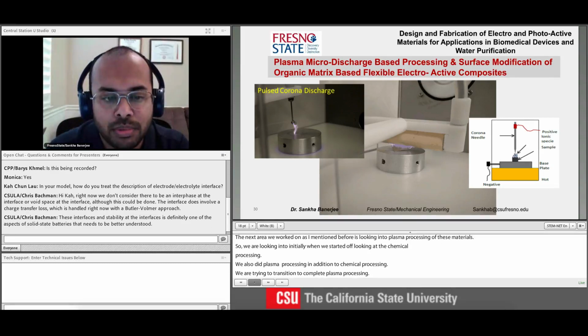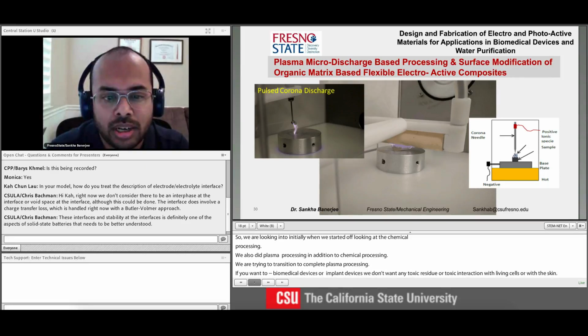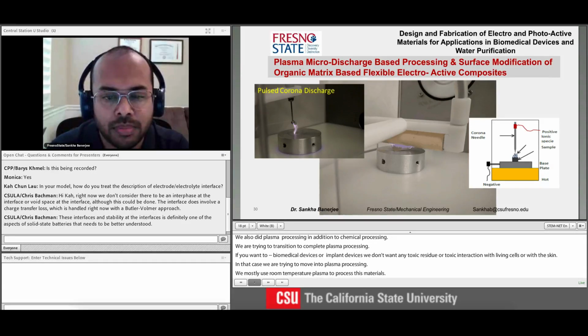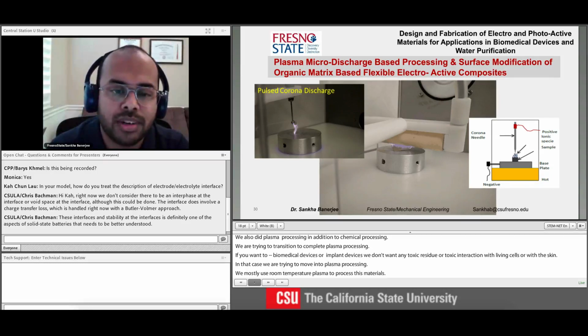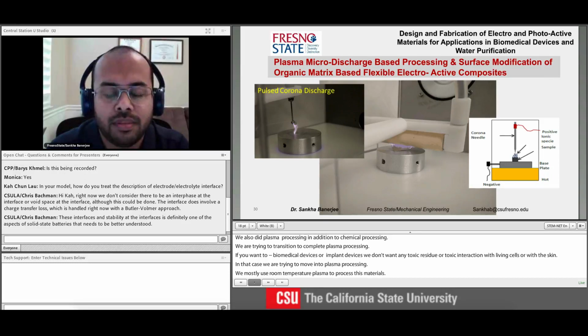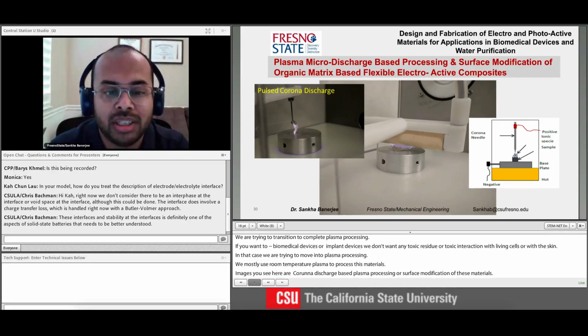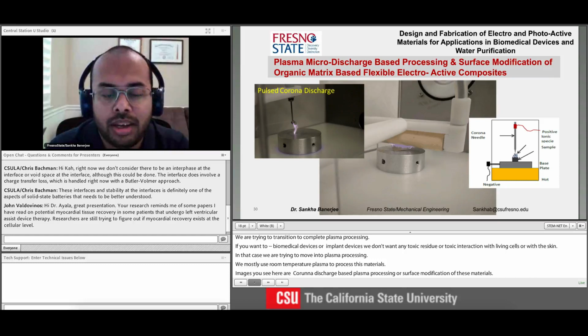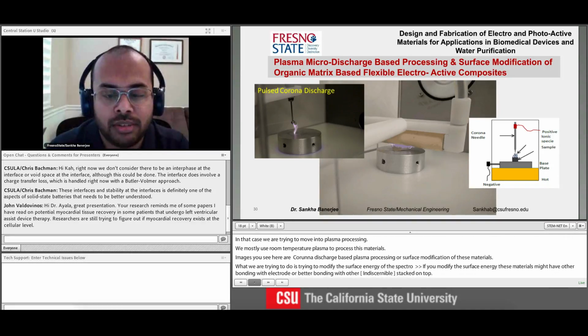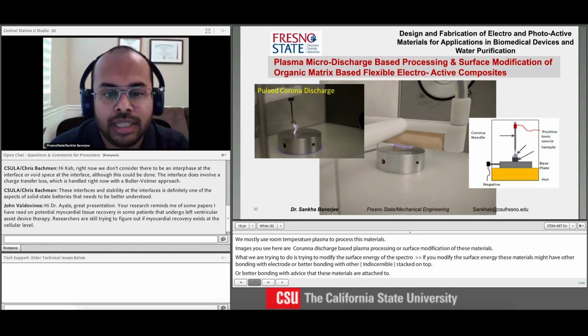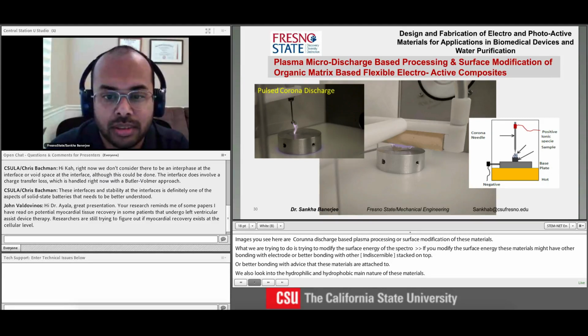We mostly use room temperature plasma to process this material. The images that you see here are corona discharge based plasma processing or surface modification of these materials. What we're trying to do is modify the surface energy of these materials. Now, if we modify the surface energy, these materials might have better bonding with the electrode or better bonding with other thin films that are stacked on top, or even better bonding with the device that these materials are attached to. We also look into the hydrophilic and hydrophobic nature of these materials, and that might also help us in developing scaffolds and also growing specific kinds of cells, and also inhibit the growth of, let's say, virus proteins.